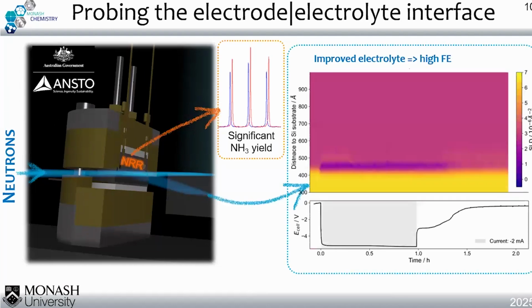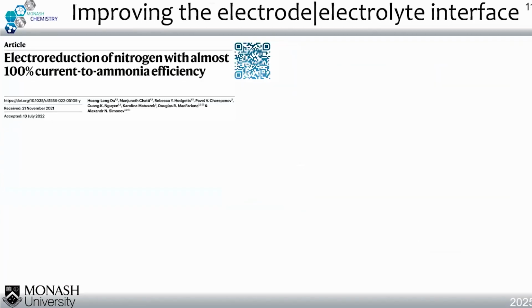So this is our example. I don't have a laser pointer here, but you can see that when you apply the current, there's lithium plating on the surface. As soon as the nitrogen and the proton contribute on the surface, we form ammonia and release the lithium back into the electrolyte, which shows the improvement of the Faradaic efficiency. So when we started understanding the mechanism, we started improving the electrolyte interface.